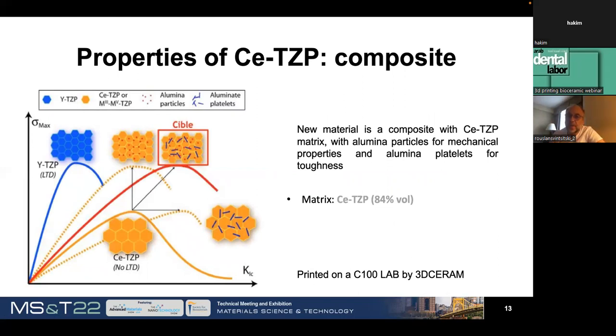this provided us the possibility to develop the target material you can see on the diagram, which at the same time has good strength and good toughness. This material is composed of 84% in volume of cerium zirconia, about 8% in volume of alumina, and about 8% in volume of strontium aluminate platelets or whiskers.